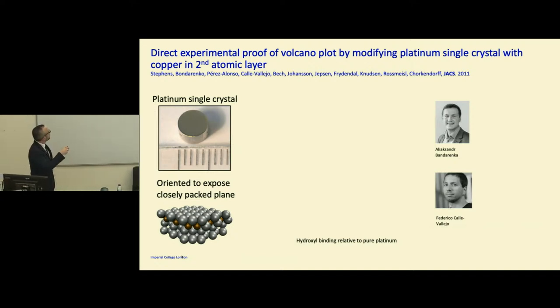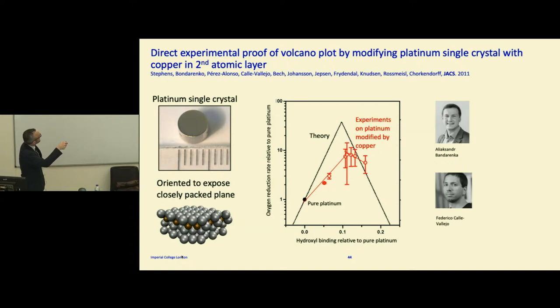And what we found is, we found some theoretical studies saying if you just put a little bit of copper in the subsurface layer, you should be able to weaken the binding of platinum to reactive intermediates. And we thought if we could just change the amount of copper, we could try and map out the volcano. And this is what we did. This is the theoretical prediction. This is the experimental result. We didn't quite reach the maximum predicted by theorists, but this is to be expected. So this is as good as we could possibly hope for agreement between experiments and theory. So this is really exciting for us to work on.